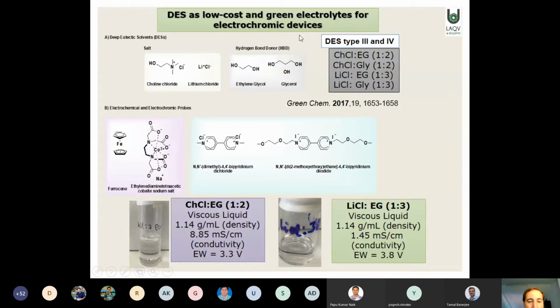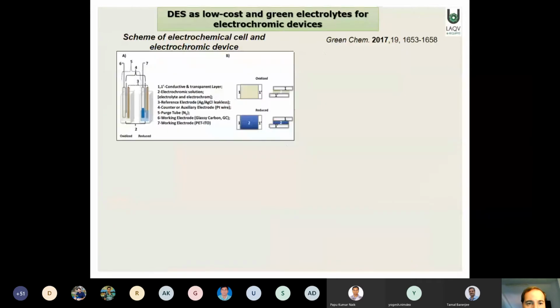For example, choline chloride and ethylene glycol, 1 to 2. This is a viscous liquid, and here you can see the density, the conductivity, and the electrochemical window, and also lithium chloride and ethylene glycol, with a relatively large electrochemical window. This is very interesting because we can apply these deep eutectic solvents as electrolytes in the presence of electrochemical and electrochromic probes like bipyridinium salts, but also ferrocene or other systems, and this works very well as alternative electrolytes.